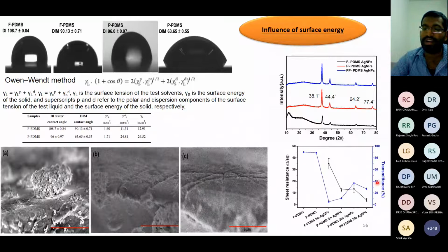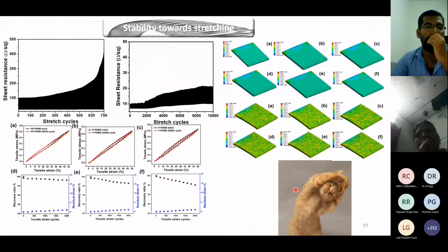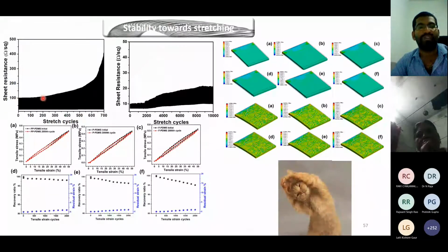And here we check the transparency versus sheet resistance for the different substrates. Here we are comparing flat PDMS, that is nothing but flat, and patterned PDMS with different timings to form the silver nanoparticles on it, like 5 and 30 seconds. Using patterned PDMS, like micro nanostructured PDMS, that is nothing but your PPDMS, within 30 seconds we are able to get a very good conductive substrate. Here you can see the differences among the two different structures.